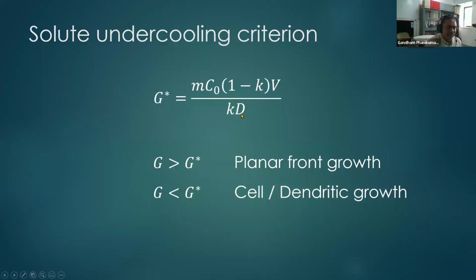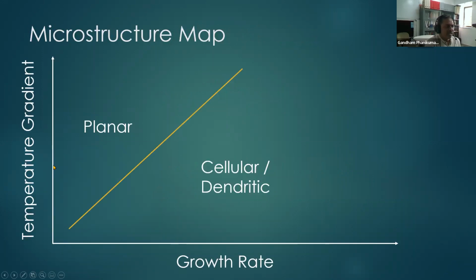And you would see that you are actually in the regime where cells and dendrites are more stable for most of the additive manufacturing regimes. So this is how the plot would look. If you increase the growth rate for a fixed temperature gradient, you will see that it would lead from planar to cellular. Or if you have a constant growth rate but increase the gradient, you can revert back to planar. So you have a way by which you can change over from one zone to another zone.